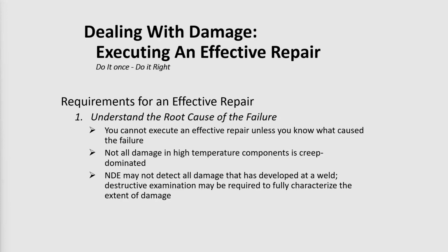Another thing that should be kept in mind is that even though you may be looking at high temperature components, not all the damage in high temperature components is necessarily creep dominated. It can be fatigue dominated, for example, and that has certain implications in terms of the repair that would be carried out. And then related to what I was talking about in the first instance, the NDE may not detect all the damage that's developed at a weld.